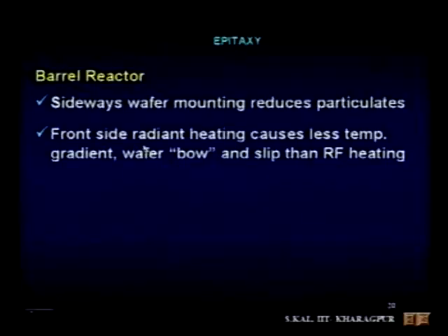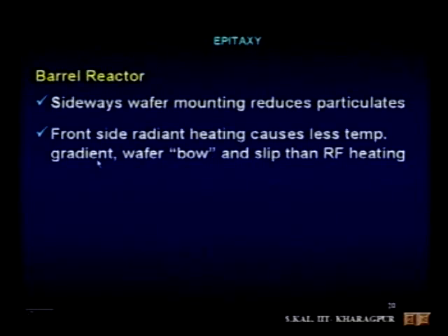Second is front side radiant heating causes less temperature gradient, wafer bow and slip than RF heating. The formation of bow is a problem in RF heating. The temperature gradient inside the bulk of the susceptor and surface will come in case of RF, but if it is radiant heating, that problem is not there. Radiant heating, from the initially the substrate surface temperature is more compared to the susceptor. Okay. So front side radiant heating causes less temperature gradient, and wafer bow and slip